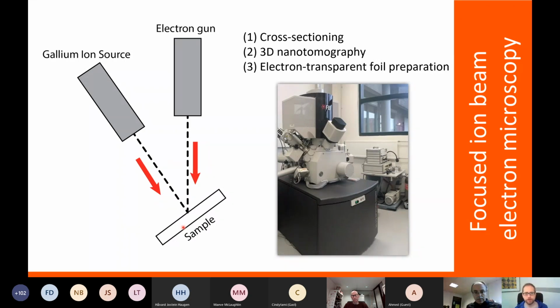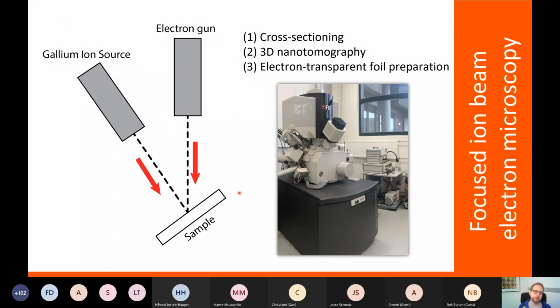And I would briefly like to discuss how we use such a focused ion beam scanning electron microscope that you see here on the right hand side in our lab in Utrecht. But what this is now, instead of only having one source, an electron gun, you also have a gallium ion source, and you can tilt the sample between the different sources to do very interesting techniques, such as three-dimensional nanotomography or the preparation of really thin samples, extremely site-specific, for later high-resolution analysis.